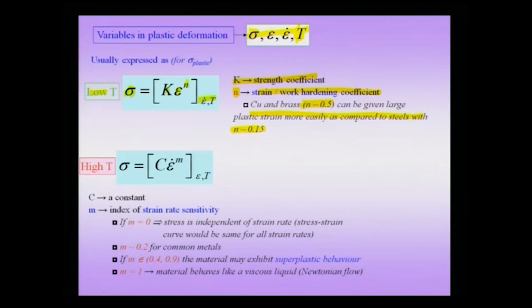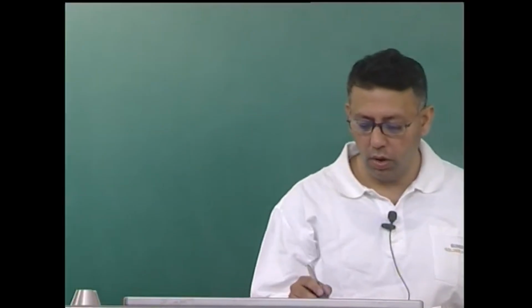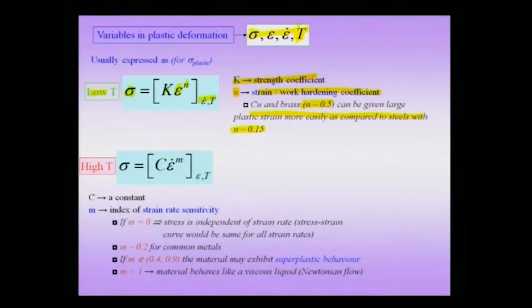At high temperatures, when we are talking about a temperature above the recrystallization temperature of the material, it is not strain which is the important variable, but strain rate. Therefore, I can write an equation for high temperature deformation as sigma is equal to C epsilon dot power m, and of course, when I do these tests, I keep the strain and temperature constant for the specimens so that they have comparable values. C is a constant and m is another important index which is called the strain rate sensitivity.